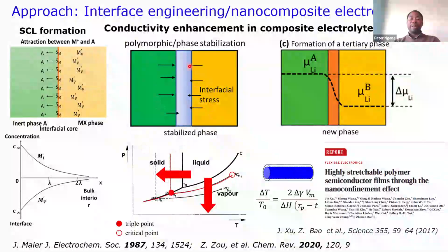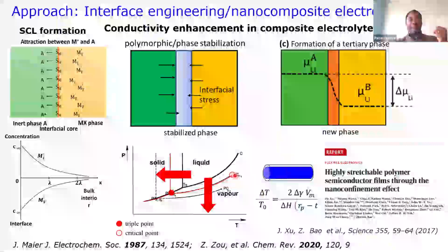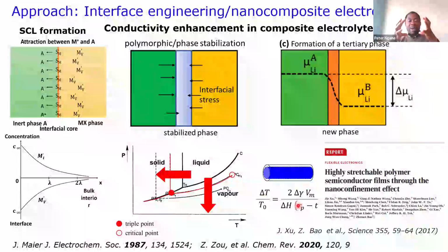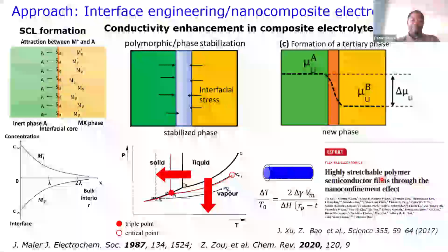And also we can stabilize some of these high temperature polymorphs at room temperature. This is given by the Gibbs-Thompson equation. Basically, we can achieve a very large depression, or decrease, in the phase transition temperature by playing with some parameters, like the radius of the material that we confine the hydride in, and the interface energy between the hydride and the scaffold. Sometimes you can even form a ternary compound at the interface. This is well known, and there is already some work done on polymer related kinds of material. So that is the idea of doing this.